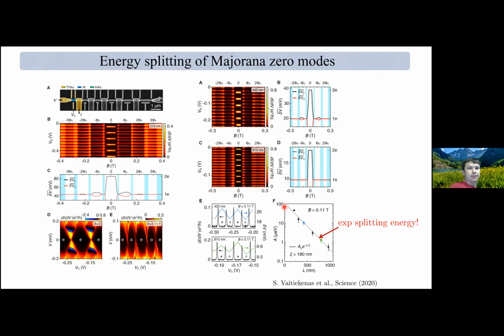So I think these two realizations of very similar physics, spinless p-wave superconductors in quasi one-dimensional systems, are very promising. They have their virtues, and one of the nice things about full shell wires is that the wire is never exposed to the outside world. During growth, the wire is covered by superconductor, and all the charge impurities that can potentially appear in the system get screened by that superconductor. So that really helps in terms of satisfying these disorder requirements.